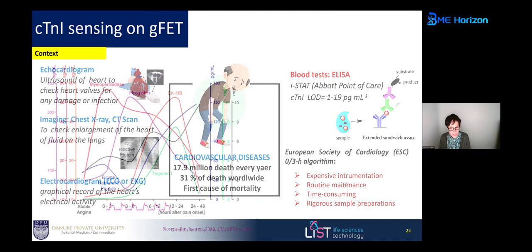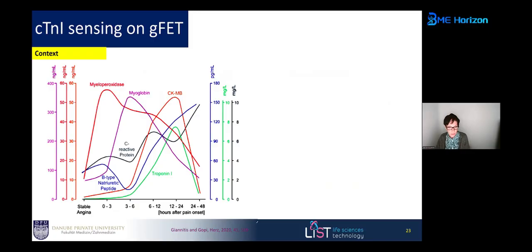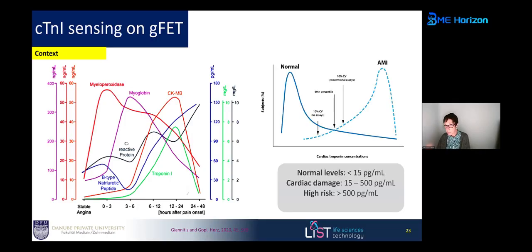So two words about the biomarkers. You can choose several biomarkers. We decided to go with troponin T and I. And the reason is the following, as you see here. When you have a cardiac problem, most people, even before they go to hospital, it will take them some time. And this is a biomarker which takes about 3 to 6 hours from the onset of the pain to show the increase. So you might be in the best position, having the maximal level of this biomarker in the blood when the patient is received in the clinic. So that's the reason we focused on this troponin.